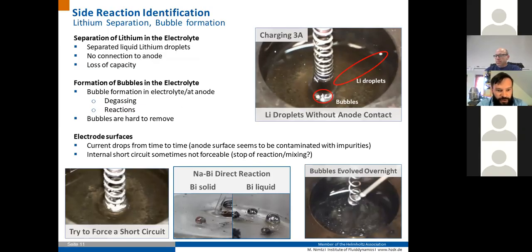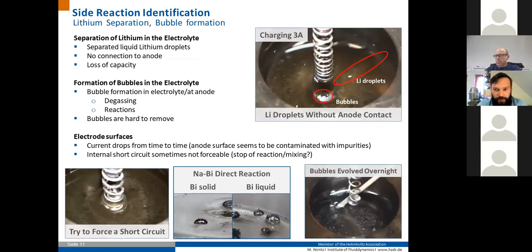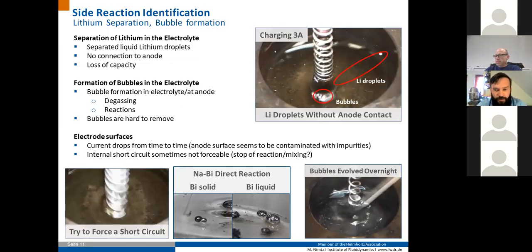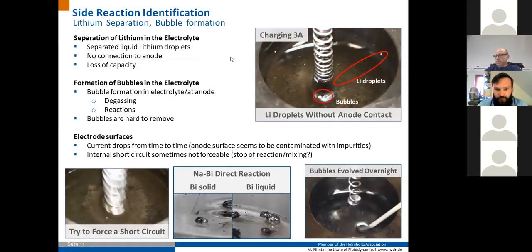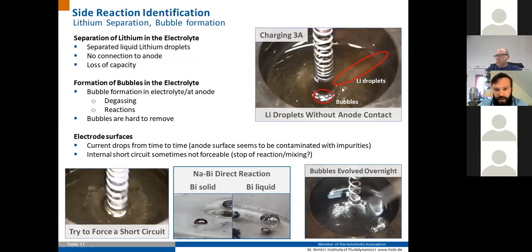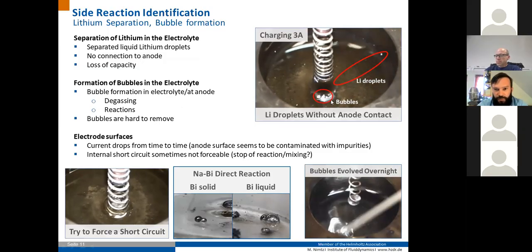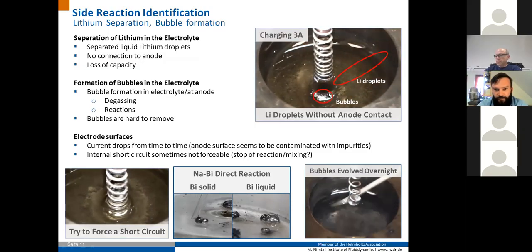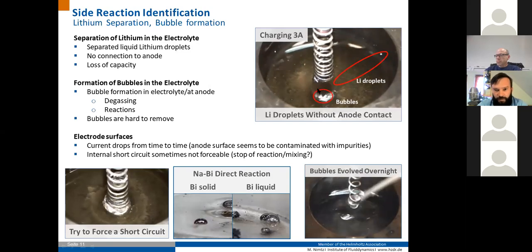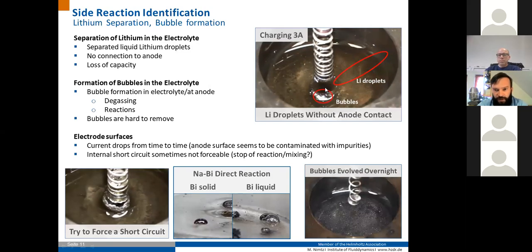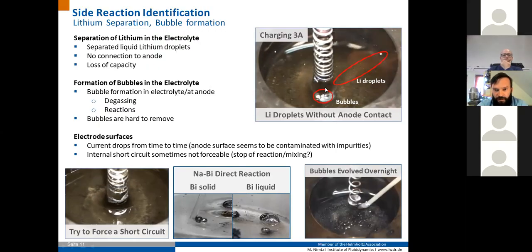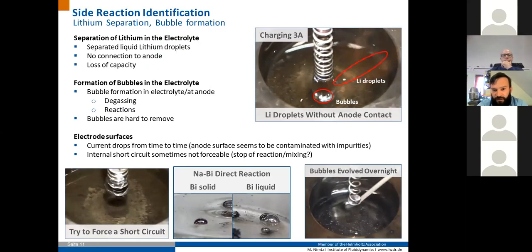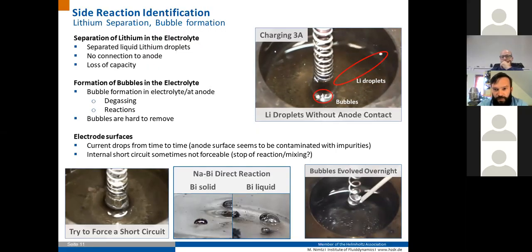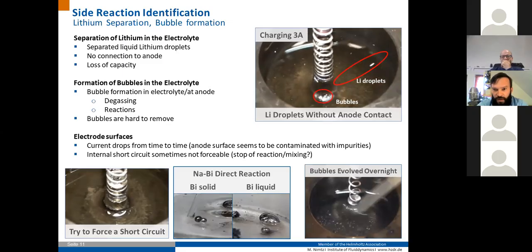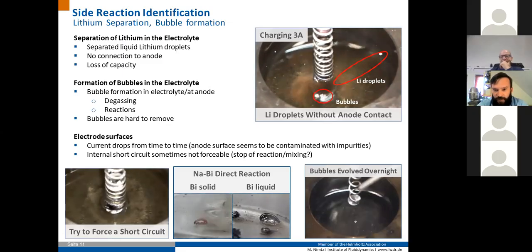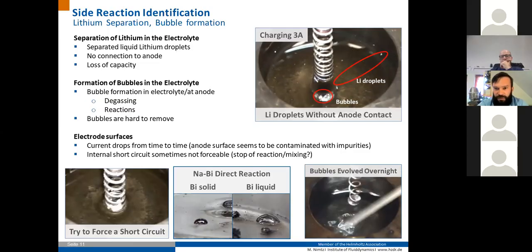Other side reactions we could observe were formation of droplets of lithium inside the electrolyte. Typically you would expect the lithium to be formed at the electrode surface directly during charging, but due to maybe metal solubility, we could observe lots of smaller lithium droplets forming as it looked directly in the electrolyte.